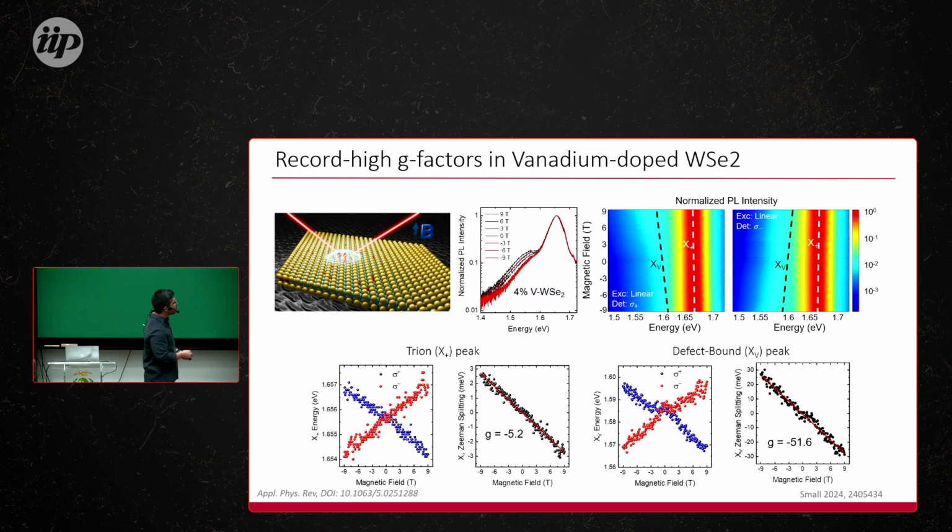And it's important to emphasize as well, if you take a close-up look over here, you can see that this is basically Zeeman splitting, all right? So it seems to be some paramagnetic behavior for this peak. The discussion is still open in the literature, because some people demonstrated it's a ferromagnetic material when you introduce vanadium, but here we are actually seeing paramagnetic behavior. So there is still this distinction. This work is fairly recent, less than 2 years old. We published this in Small.